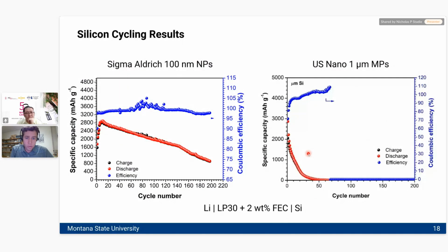It has a lot of issues with stability, and it does show high capacities early on, but that rapidly gives away to much lower capacities, and in some cases, almost zero by the time you get out to 50 cycles.